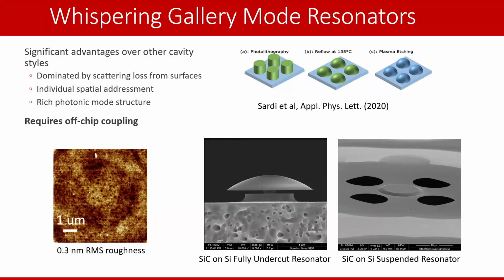If you have low implantation doses randomly implanted in your silicon carbide, they will not often end up in your cavity mode volume. And that's a problem because then you can't couple to them. So you can make wonderful cavities with excellent small mode volumes, but if there's no defects that live in the mode volume, it's useless. So for this reason, and because of some fabrication constraints, we decided to use whispering gallery mode cavities to host these defects for doing cavity QED.